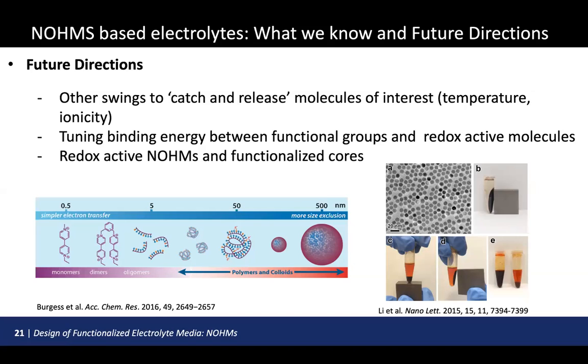Actually, the other student, Tony, is working on something similar. What happens is we cannot use NOHMs as a pure form. Lynden Archer at Cornell uses the almost pure form, so his material is almost gel-like, like a solid electrolyte. But our material is a very low viscosity fluid, made by adding a secondary fluid. And what we found a few years ago was, if you have a mixture of nanoparticles with the polymers with the water versus NOHMs with water, we totally thought that the viscosity would be higher with the NOHMs because there's a whole bunch of nanoparticles.